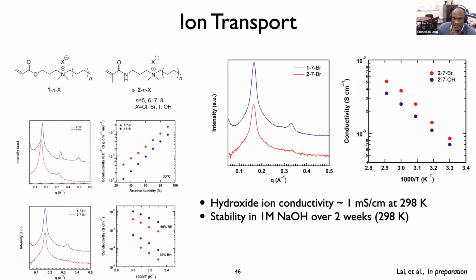Obviously here, stability under strong basic conditions is a strong consideration. And so we've been modifying the chemistry of this molecule, getting rid of this ester linkage and looking at an amide chemistry. And we've seen thus far that the transition to this amide chemistry has provided us with fairly good stability. Here just tested over 2 weeks at ambient temperature. We're now moving up to higher temperatures. And we have a fairly reasonable hydroxide ion conductivity, not world beating by any stretch, but certainly good enough to start to think about the potential of these materials in electrochemical devices.